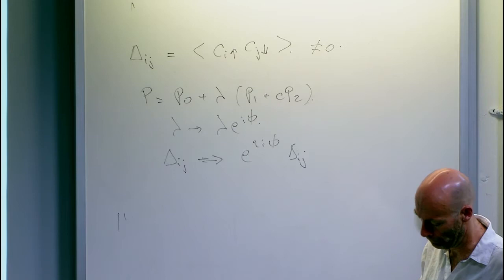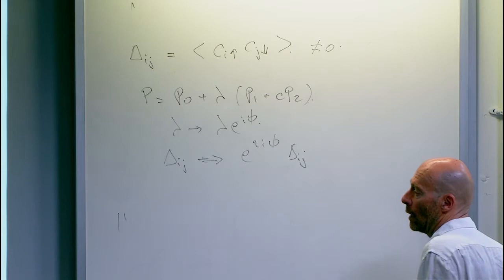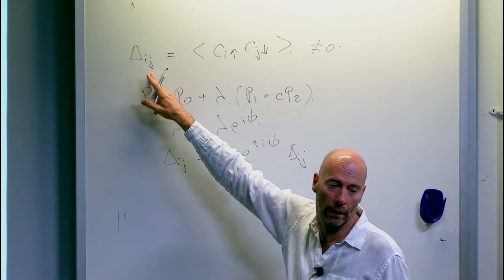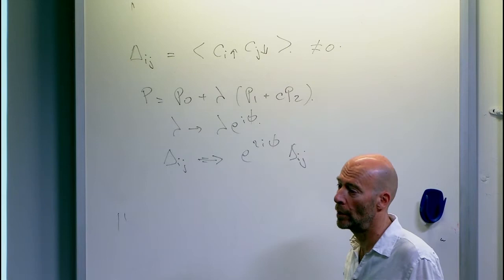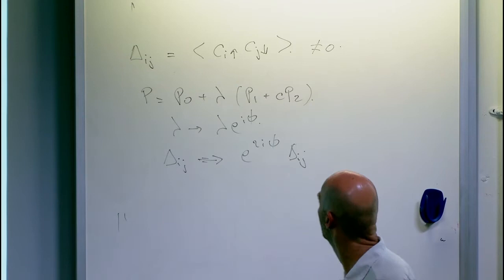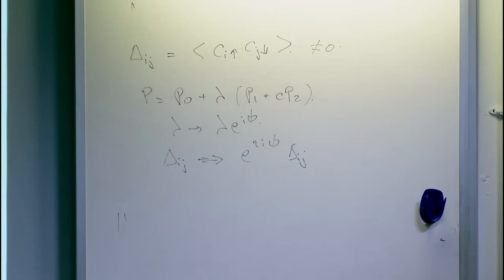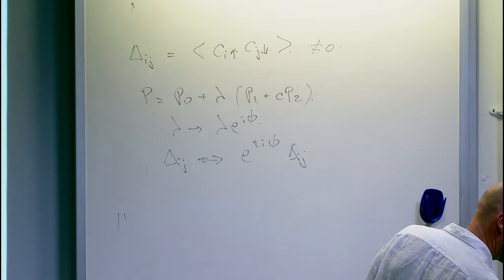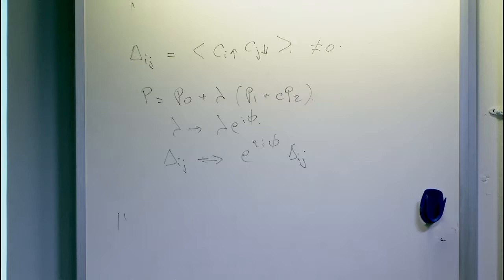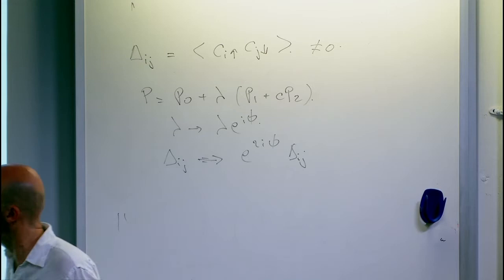So what you can do with that, you can do all sorts of things. For example, you can calculate how the superconducting order parameter appears as a function of doping. How much time do we have? Two minutes? Yeah, we started a bit late. Two minutes, maybe. So how the superconducting order parameter appears as a function of doping: what you see is that it appears immediately when you dope the system, at any finite doping. So you can even try to fit the dependence of the superconducting pairing amplitude. This is what I showed here. So this is the pairing amplitude on the nearest neighbor sites, and you see that basically it goes like a square root of the doping. The different curves correspond to different values of the parameter c that we have in the ansatz.